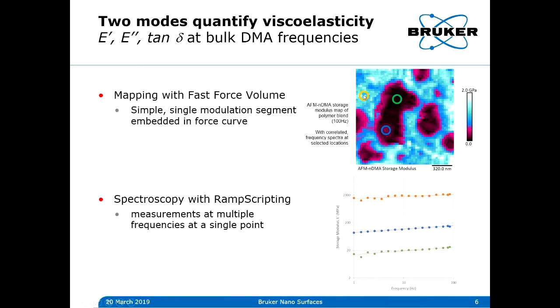But you can also go and choose separate locations on here, and we can do spectroscopy at user-selected points, and that gives us a series of measurements at different frequencies. So down below here you have a plot of the frequency for each of these circled areas, and we have storage modulus versus frequency for each one.